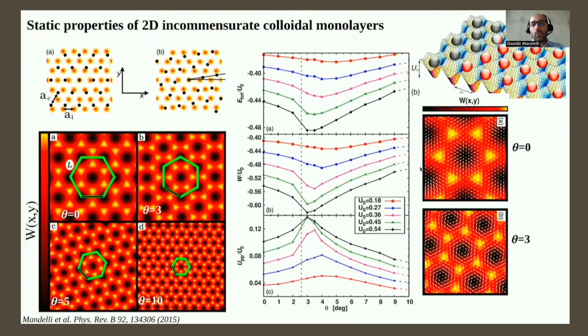We can look in even more detail at what is going on. Here what I'm showing is the vector field that corresponds to the displacement of the particles from the unperturbed lattice to the fully relaxed one. And we see that for the theta equals 0 configuration, there are mainly longitudinal modes involved in these distortions, which are very costly and do not allow particles to move very much, trying to get closer to the minimum of the substrate potential. Instead, as we rotate the colloid, this vector field shows that distortions mainly involve soft shear modes that allow relatively larger distortions, and so allow the colloidal monolayer locally to reach a better interdigitation with the substrate.